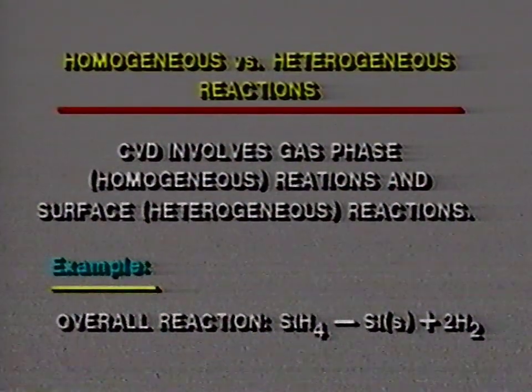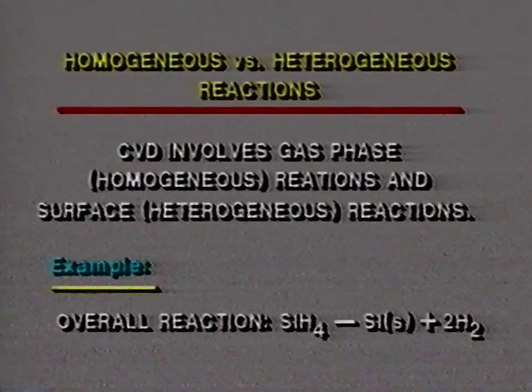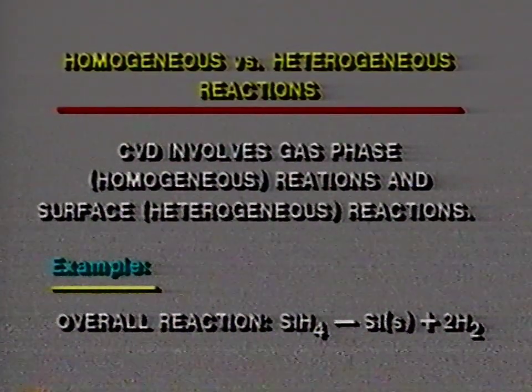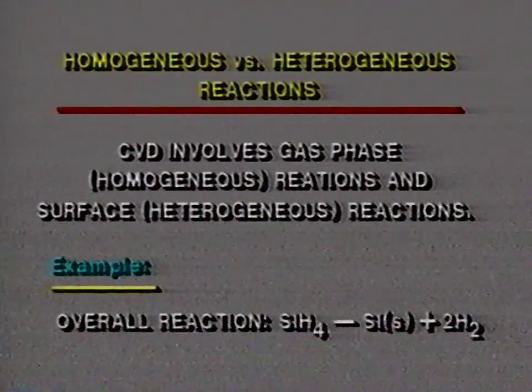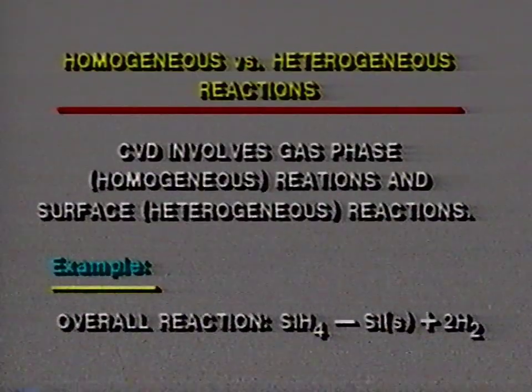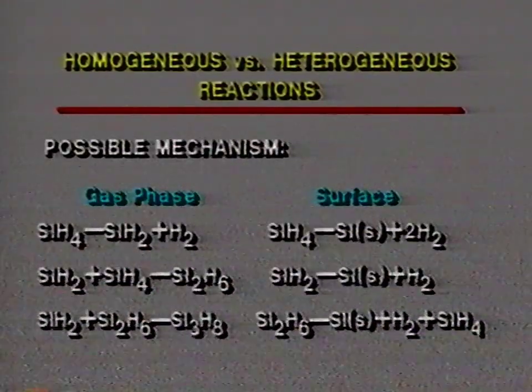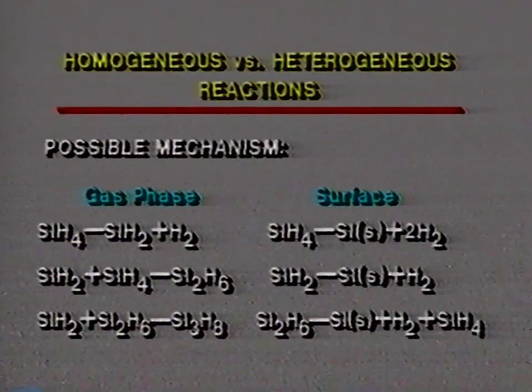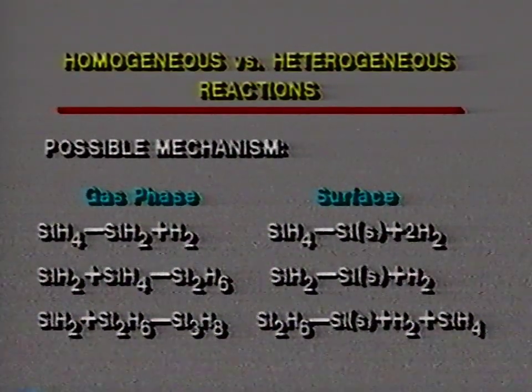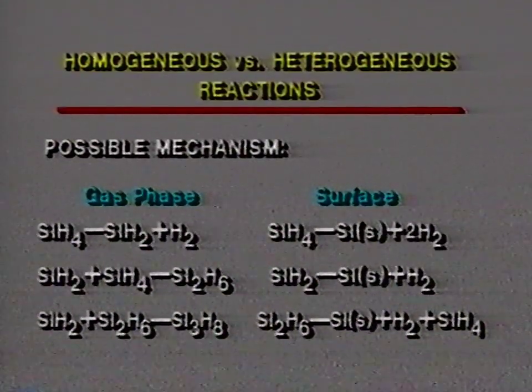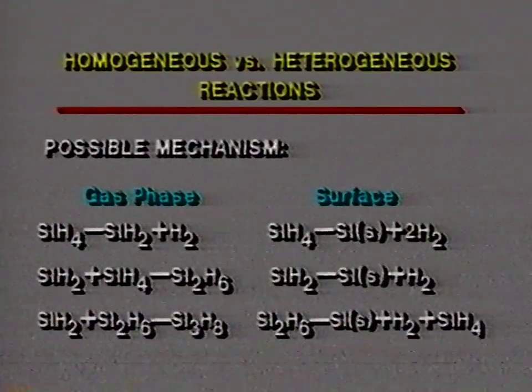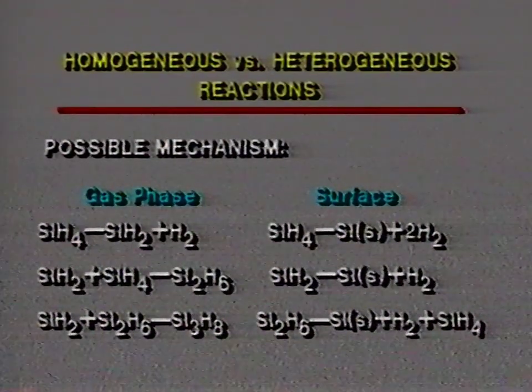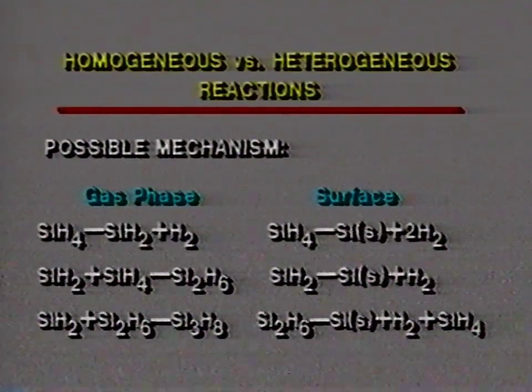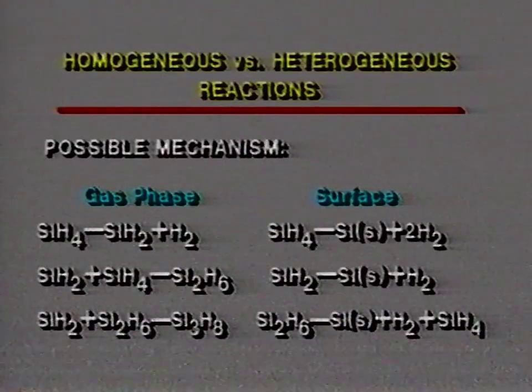Let's have a little closer look at the important homogeneous versus heterogeneous type of reactions using a very simple example, in this case the silane pyrolysis to silicon and hydrogen. We have essentially two types of possibilities. We have the gas phase reaction or we have the surface reaction. In the gas phase, what happens is silane dissociates to SiH2 and hydrogen, which then reacts further with silane to produce disilane or Si2H6. Alternatively, we have a build-up into higher silanes as shown down here to Si3H8.